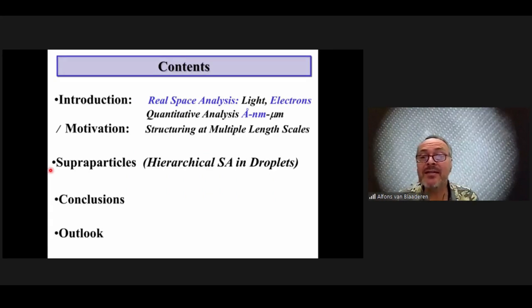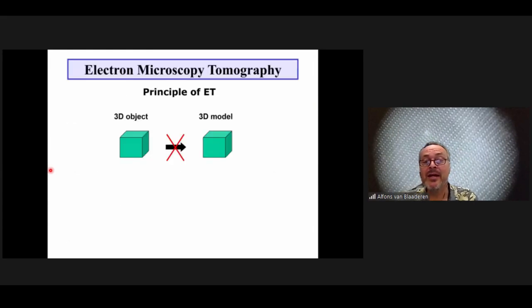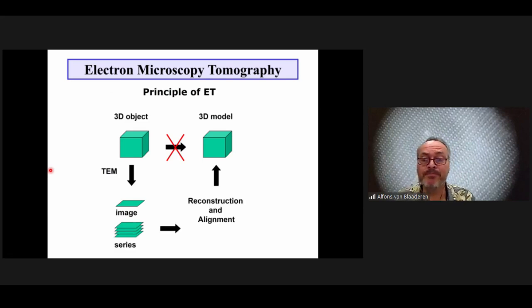So that's on the light length scale, and we're pushing that all the way down to 100 nanometers. But we also want to analyze structures on the nanoparticle length scale, so just particles of 10 nanometers or less. With light microscopy and confocal microscopy, we make use of the very high numerical aperture of the lens. Here in electron microscopy tomography, and this is actually an extension of the technique that you may know from tomography done in the hospital, but then on a much smaller length scale. The numerical aperture is very small, so it means that a lot of the data is in focus. Several microns can be in focus, so we can turn the sample around, get different projections for different directions, and obtain 3D data sets that way.